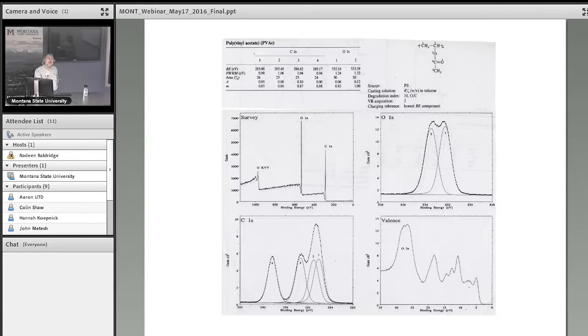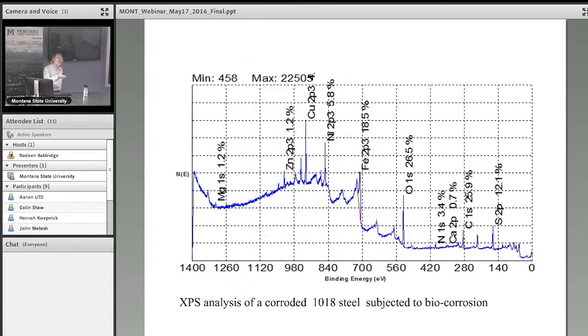So here is the spectra I took from that very complicated surface. And then I look at core levels. I'm not going to show them here. So I know exactly where sulfur is supposed to be. Is it the sulfide or sulfate? Sulfate is plus 6, sulfide is minus 2. There is a huge difference. So by looking at the core levels, I can tell it was iron sulfide or copper sulfide. That's how we tell.